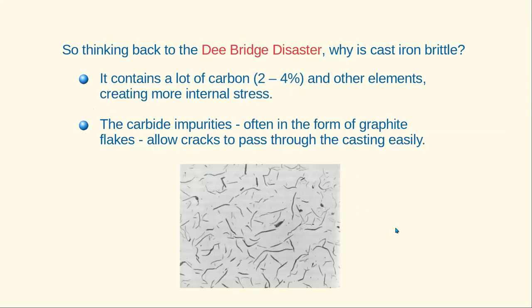So thinking back to the Dee Bridge disaster, why is cast iron brittle? It's brittle because it contains a lot of carbon and other elements, creating more internal stress. The carbide impurities, often in the form of graphite flakes, allow cracks to pass through the casting easily. Cast iron contains a lot of carbon. What's the difference between that and steel? Steel is much purer and has very little carbon, but enough to produce some precipitates that cause strength. But it doesn't have the brittleness of cast iron, which has a lot of carbon.